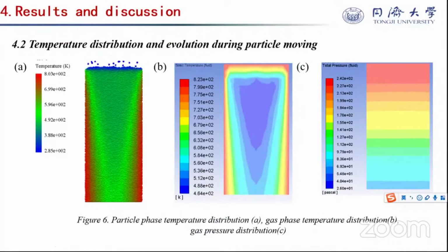The figure in the middle gives the gas phase temperature distribution. After the gas enters the reactor, it cools down sharply, and at the same time it is heated up by the wall temperature, forming a temperature distribution with high boundary temperature and low center temperature.